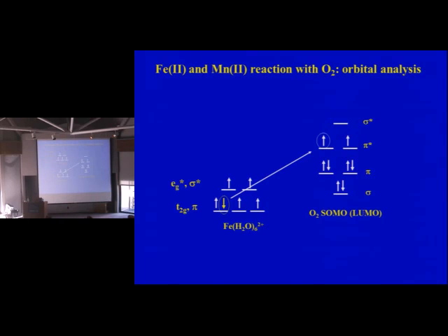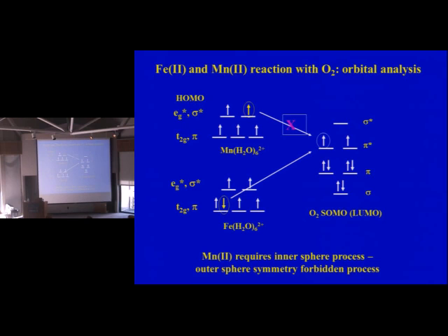In this case, for manganese, you're going to take an electron from a sigma. So you actually have a different orientation. The pi electrons are above and below the plane or the bond axis. So if I have a sigma electron coming in on the bond axis, it's not going to interact with the orbital, so I can't have electron transfer. Outer sphere. So for manganese, the process would have to be inner sphere, and when you raise the pH, you get manganese hydroxide rather than manganese 2-hexaaquo, and then this becomes favorable.